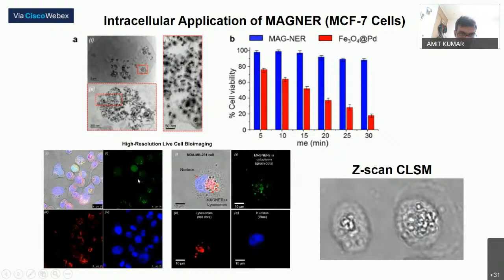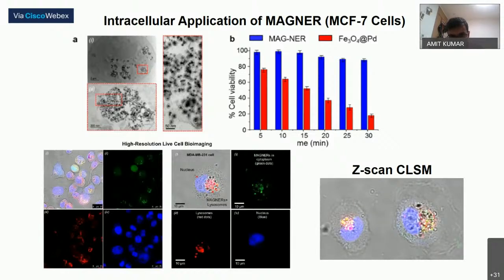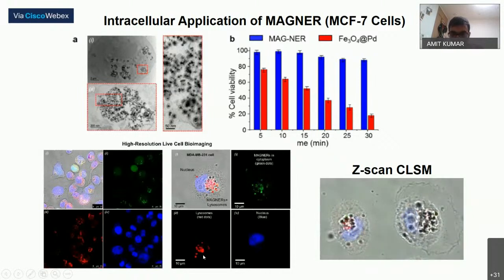So these are high-resolution live cell confocal images of the cells fed with nanoparticles. We modified these nanoparticles with the FITC dye and tried to locate where they go after internalization. So in the depth scan CLSM image, we could clearly locate that the position of the nanoparticle is not on the membrane, it is actually inside. And the red colored spots are actually lysosomes. So we visualized them with the LysoTracker dye, and we could see that some of the particles are also present in lysosomes. So maybe the possible pathway of internalization of such particle is endocytosis, and then endosomes fuse with the lysosomes in the final stages.